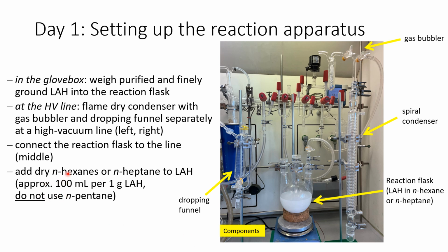Finally, we add dry hexane or heptane to the lithium aluminium hydride in the reaction flask. Here, approximately 100 milliliters of solvent should be used per gram of lithium aluminium hydride. Importantly, you should not use pentane but solvents with a higher boiling point, such as hexane or heptane.